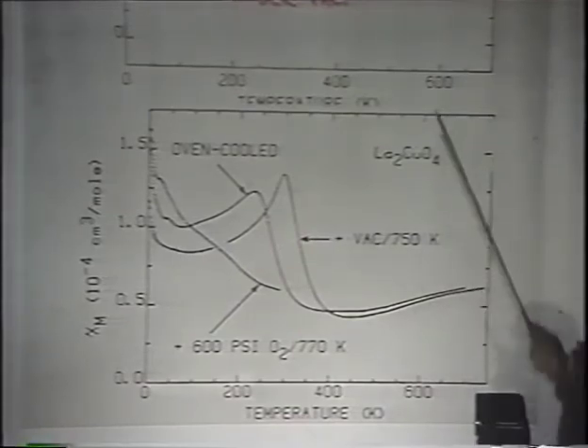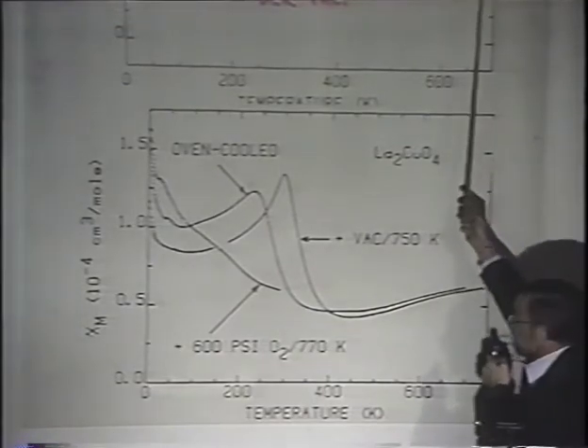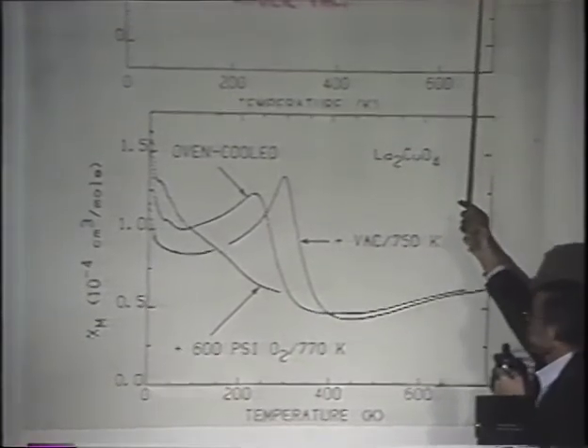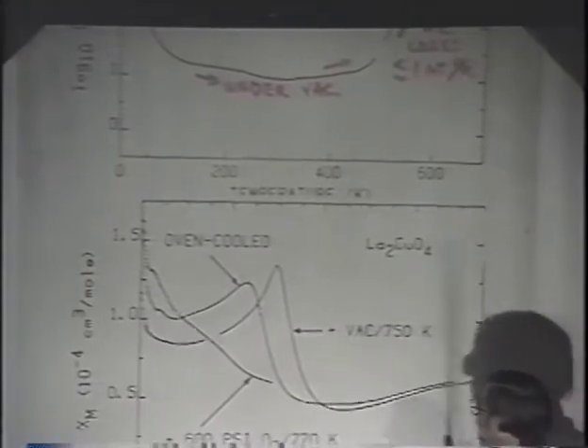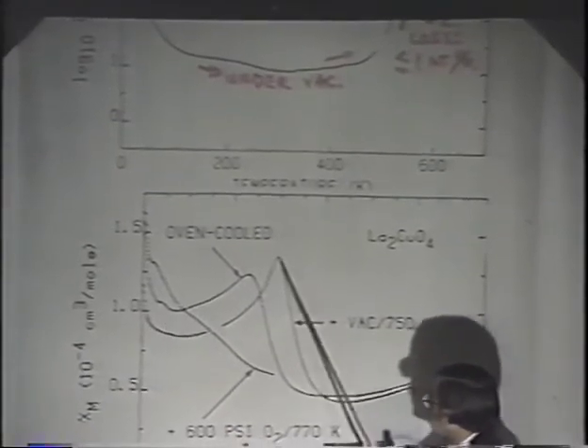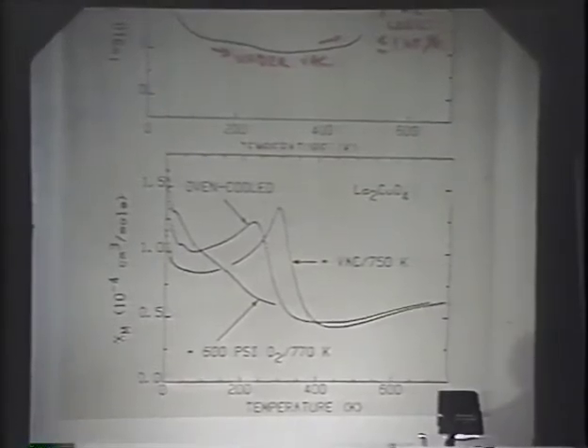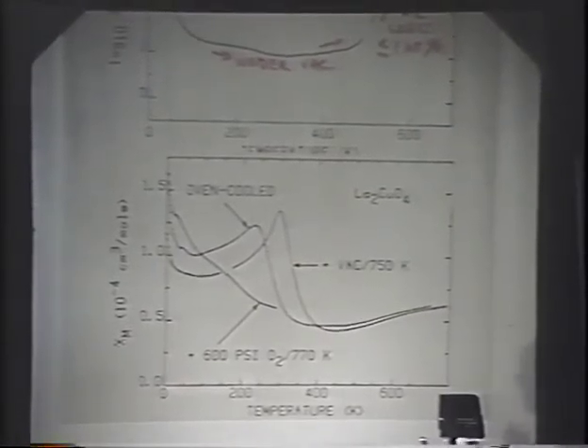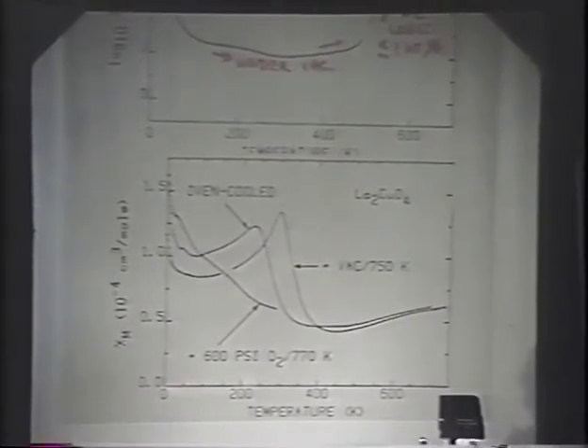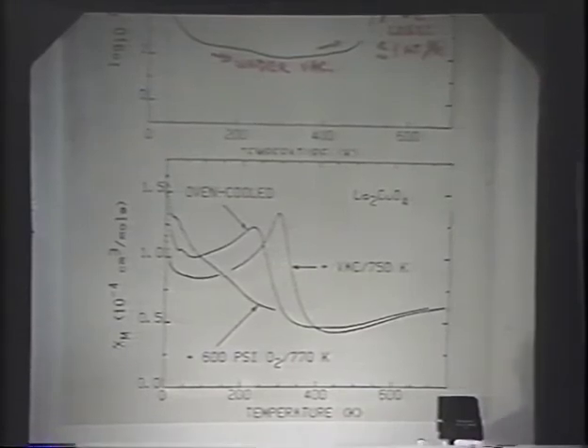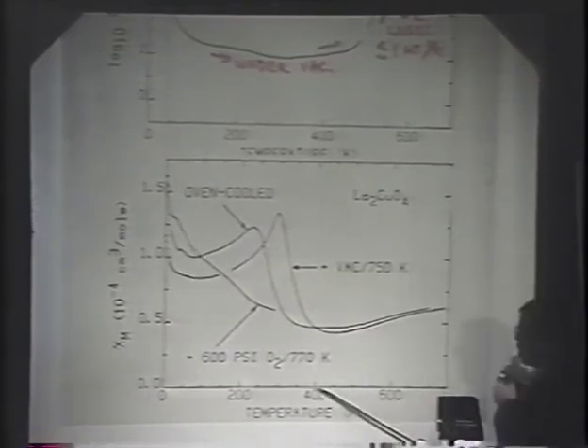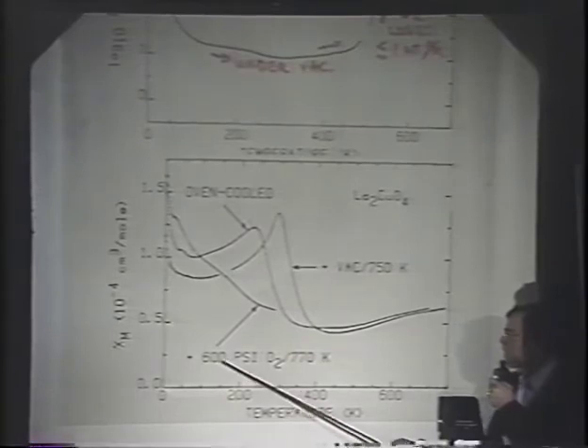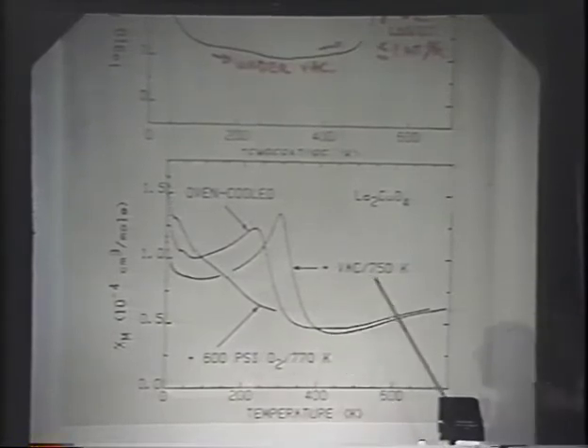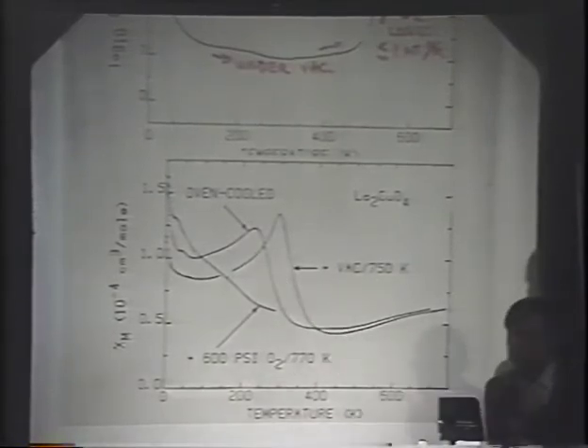However, if you take the sample that we ran up to 750K under vacuum and run it, what you get is this curve. So clearly, the magnetic interactions are extremely strongly related to the oxygen stoichiometry. But you can also go the other way. If you put the sample under 600 pounds of oxygen at 770K, essentially it disappears.